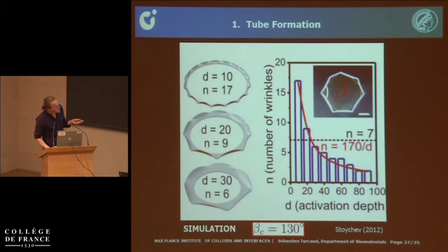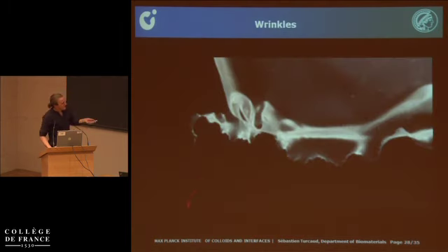Another question we had in the experiment is that at some point it stops. For example, if you start with a circle and you switch temperature, it will start to wrinkle from the sides, but it won't just wrinkle and wrinkle like in the simulation. It will stop at a given, critical angle of 130 degrees, for example. We don't quite understand this completely now, but I think it stops when the bilayer touches the flat part again.